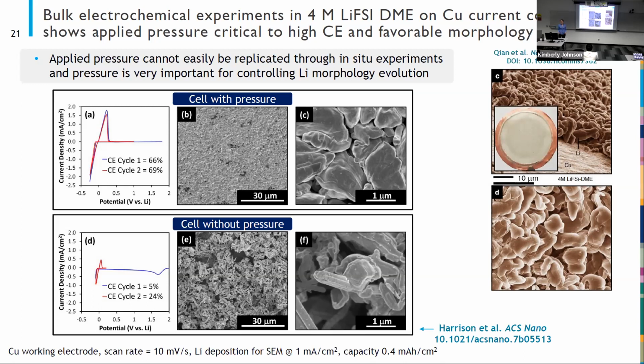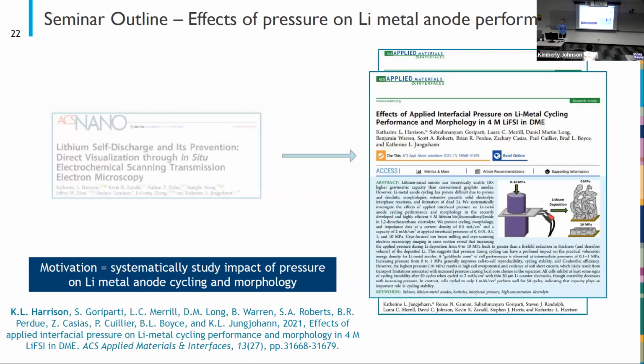So what this tells us is that even in these really promising high concentration electrolytes, we are still having problems with dendritic growth, and pressure is a critical parameter for controlling this lithium growth. So in that paper, we saw that pressure mattered. We know that that's important, but we didn't quantify the pressure in any way.